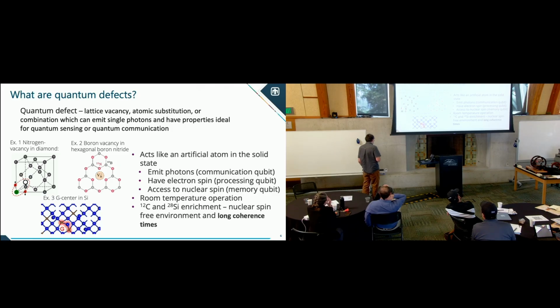Another defect that we've been using recently is the boron vacancy. This is just the absence of a boron in hexagonal boron nitride, which is a 2D material that you can exfoliate. So one might imagine how that could be useful as compared to a bulk diamond. And another example is a G center in silicon.